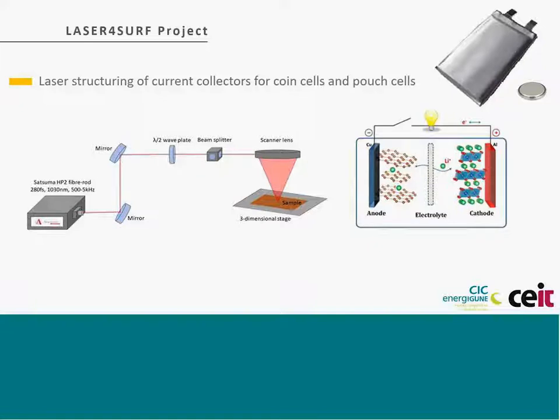How do we do this? Just by scanning the sample with an ultrafast laser. We scan the sample in this way so that we apply different lines to the sample, and these nanostructures are generated automatically. So they are self-ordered. We do not need to move the scan by 800 nanometers each time. We just write a single line that contains lots of these 800 nanometer lines. And we are applying this to the current collectors, both the copper and the aluminum, not only for coin cells, but also for pouch cells, which are this second shape of cells you have here.